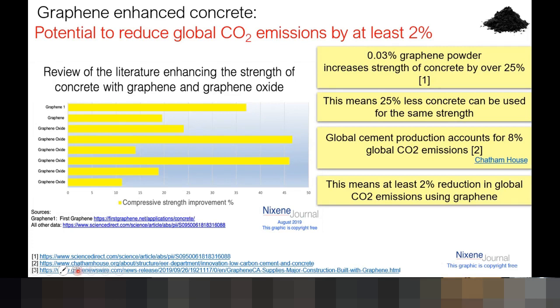Yeah, just very quickly, this is a review of literature done with putting graphene and graphene oxide in concrete. So this is raw data that you're seeing. You're seeing different graphenes with the horizontal bars, and then the compressive strength improvement along the bottom. Some of these are approaching 45 to 50% improvement in strength. There's a lot of variability between the different tests at the minute. That's probably, we think, because of the way the graphene powders and dispersions are mixed with the concrete.